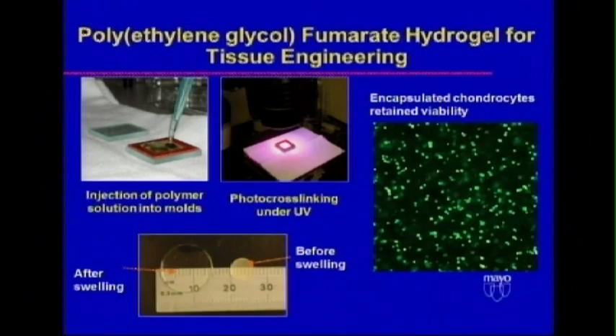But we thought, with respect to trying to get cartilage to regenerate, cartilage is aneural, avascular, and alymphatic, and the cartilage cells live by diffusion. We thought that if we made a hydrogel, maybe the cells could stay alive a longer time. And I asked Maruk to try to make this hydrogel. She made it with a short PEG chain, and we now call it oligopolyethylene glycol fumarate, OPF.